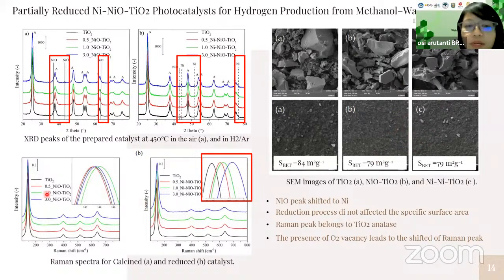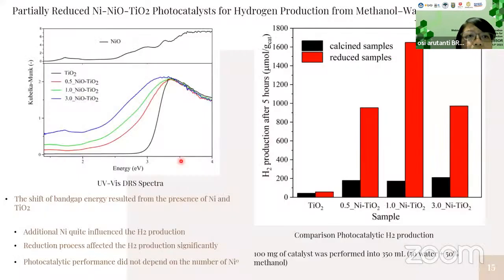Here we can see the Raman spectra, this is for the calcined catalyst. We can see the peak of titanium dioxide is almost similar when adding Ni. However, the reduction process makes the peak of titanium dioxide shift. It can be assumed that the presence of oxygen vacancy due to the reduction process resulted in the shift of the titanium dioxide peak.